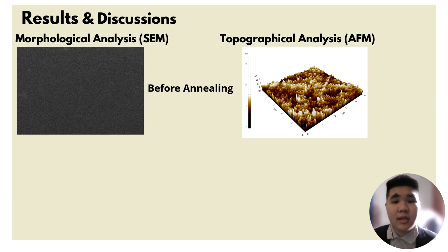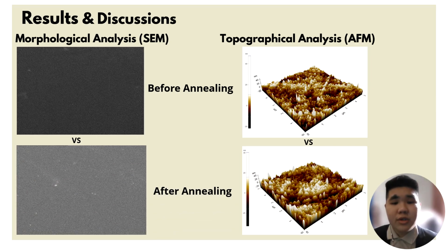Moving on is our morphological analysis, where the top row shows the unannealed samples. As seen in both the SEM on the left and the AFM on the right, the surface is smooth but lacks connectivity. However, the bottom row shows the optimized samples. Here we see significant grain growth and sintering. These larger conductive islands are exactly what created the high conductivity pathway we measured.